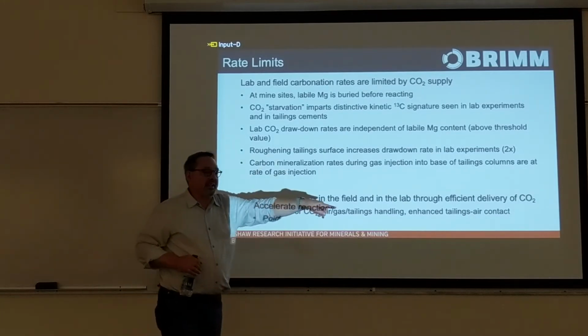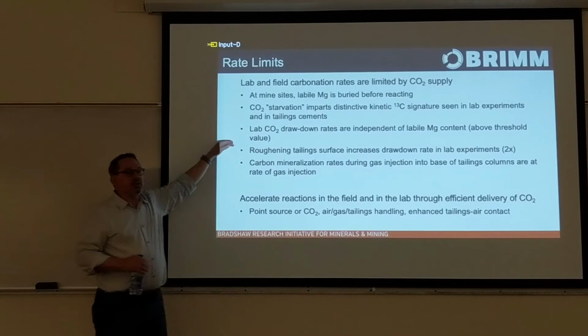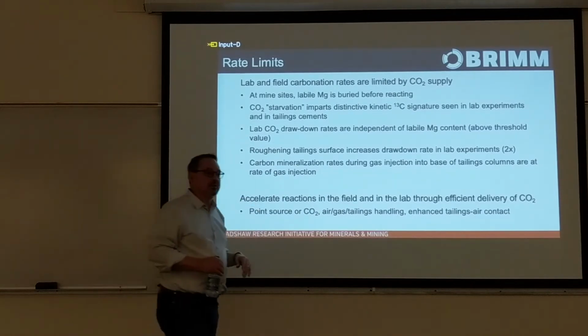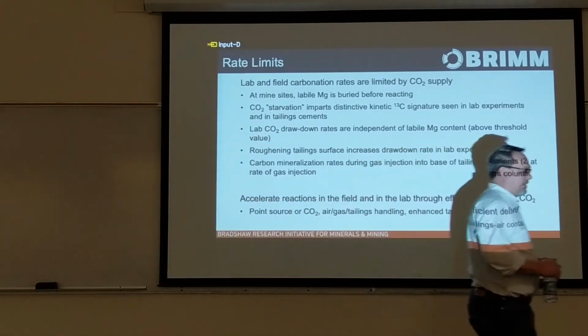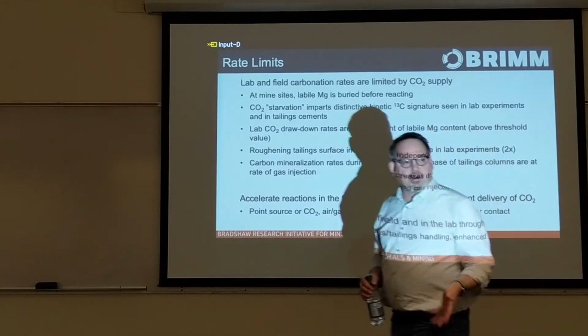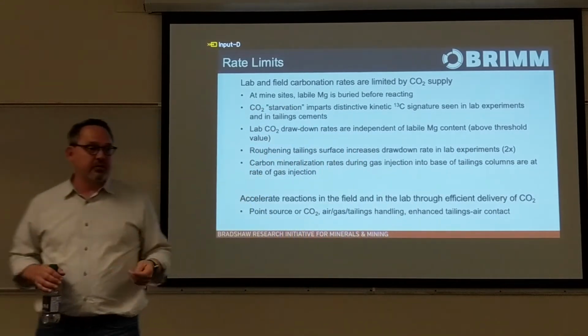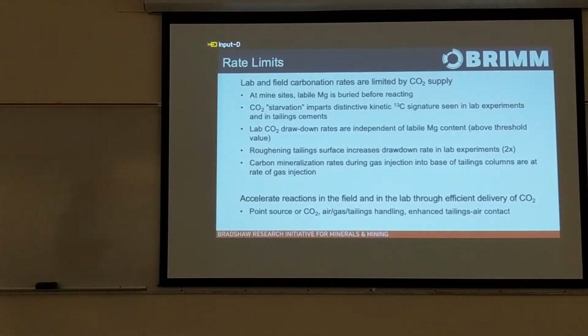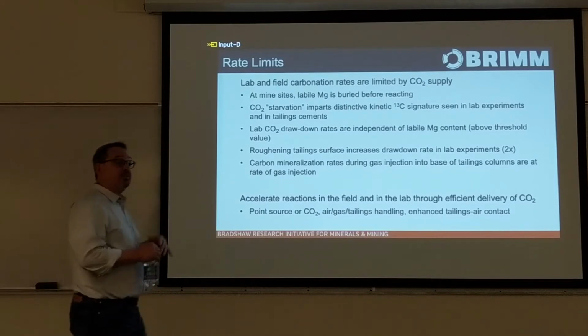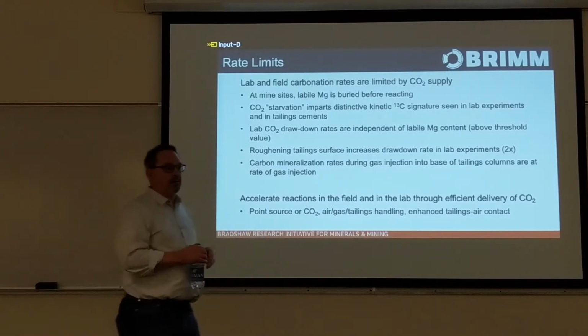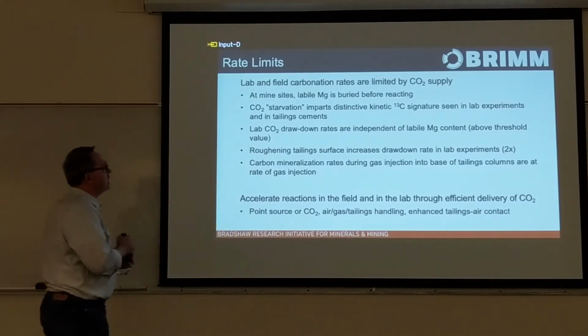When we run experiments like this, we find that the drawdown rates are independent of the amount of reactive material. So if we triple the amount of reactive magnesium in these tailings, we get the same drawdown rate. And the reason for that is it's transport limited. The rate is controlled by the diffusion of CO2, not by the reaction at the interface. If you had 3 times as much interface, you'd expect the reaction rate would triple if you had more labile magnesium in that material.